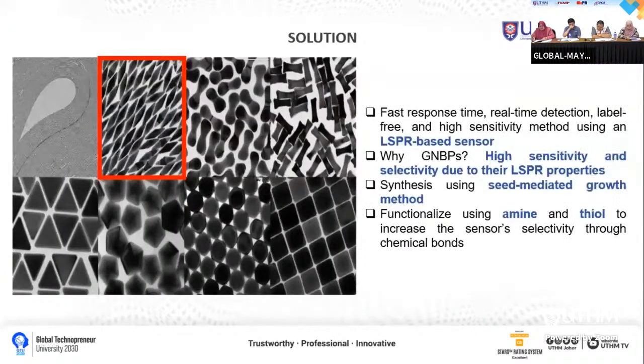We can utilize the LSPR phenomenon possessed by GNBPs to detect glucose. This method has a fast response time, real-time detection, is label-free, and has high sensitivity to surrounding medium change. As sensing material, GNBPs are chosen due to their high sensitivity and selectivity. Then, the seed-mediated growth method is used for the synthesis. We functionalize GNBPs with amine and thiol, because glucose is a carbohydrate molecule. It is important to use ligands so the GNBP surface can bind with glucose properly through chemical bonds.